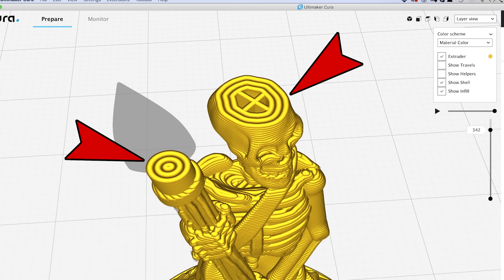So if you look at this image, in the case of the skull of the skeleton, three layers will print on both sides, and I've got infill cranked up a little bit here, so it gives it a supporting structure. In this case, the infill is not for strength. It's to give a lattice work for printing the shells on, which will actually help you with things like overhangs. But if you look at the more critical area, the spear cannot really print with three full shells on each side. It is close there to three, but it's not getting any infill at all. So even if you were printing your miniature with a complete solid fill, you're not going to get any more strength in critical areas like legs and ankles and weapons than you would with just a straight three layers because they're not thick enough.